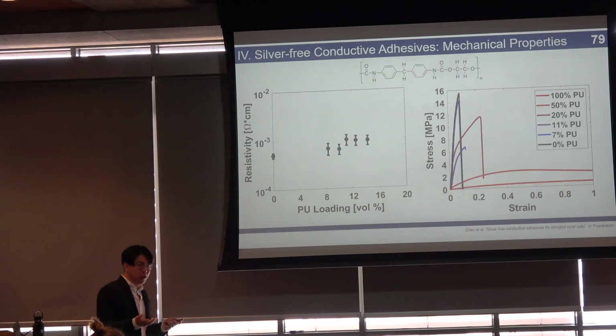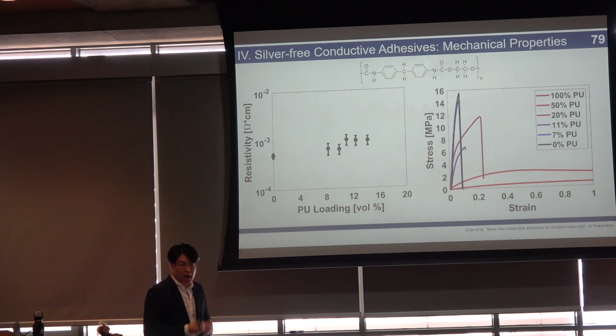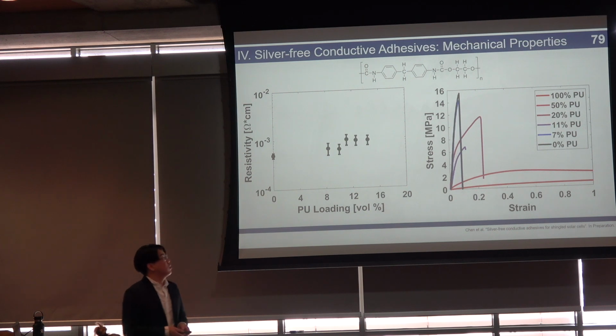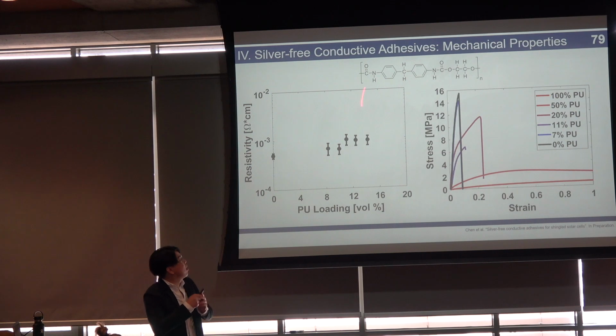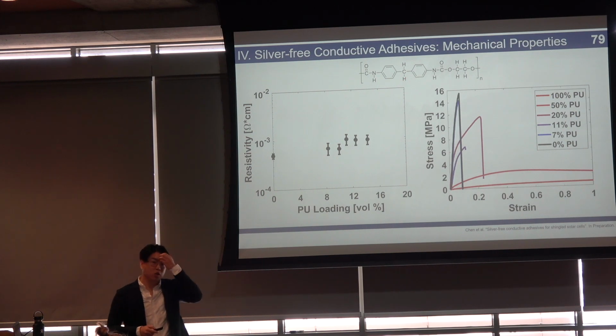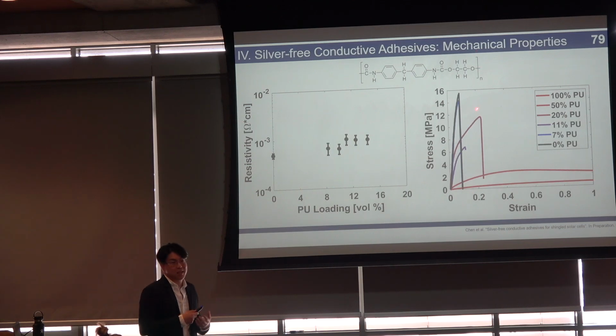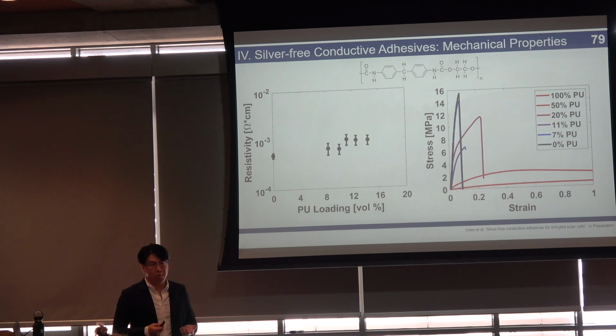So right now what I'm working on during the rest of my time here in the group is actually trying to solve this problem. One of the approaches we're taking is we're blending PEDOT:PSS with this commercial polymer, polyurethane, which is commonly used in adhesives and coatings. And we're trying to use a blend to manipulate the adhesive properties without drastically decreasing the electronic behavior of the material.